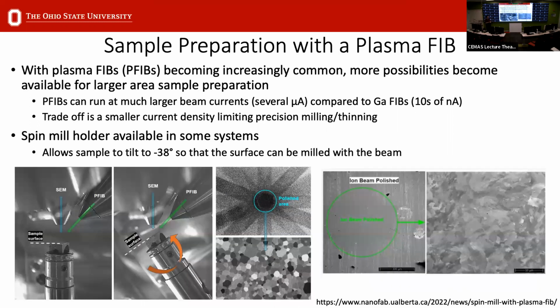Plasma FIBs are becoming increasingly more common. The difference between these systems is that they use a plasma, usually xenon plasma, instead of gallium. The biggest difference between a gallium FIB and a plasma FIB is that the plasma FIB can run at much higher beam currents, typically on the order of microamps, compared to gallium FIBs, which are on tens of nanoamps. So you can do a much larger area. The trade-off is you have a smaller current density.